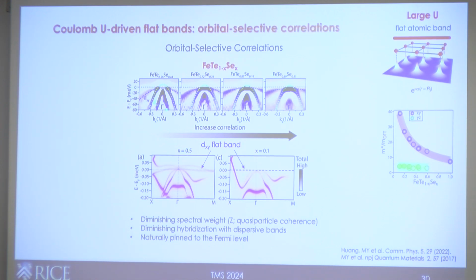Near the gamma point, this is energy versus momentum, you see 3 hole bands, right? And then if you tune the amount of selenium from one end to the other, what you see is that the curvature of these 2 inner bands doesn't change very much. But this outer one actually visibly changes from one end to the other. And the curvature, as you know, is related to the effective mass. So you can extract that directly by fitting these bands. For the inner 2 bands, this is the mass enhancement, the effective mass divided by the mass you get from the DFT calculation. For the inner bands, they don't change, but for this one, which happens to be the XY orbital, you can see its effective mass enhancement actually diverges towards this end. This is iron tellurium.